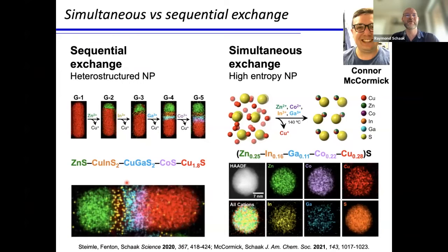And then finally, just to kind of show there's more than meets the eye to some of this, I showed these sequential partial cation exchange reactions that led to heterostructured nanoparticles. This is a 5th generation particle containing zinc sulfide, copper indium sulfide, copper gallium sulfide, cobalt sulfide, and copper sulfide. But if you do effectively that same type of exchange with the same cations simultaneously, where all metal cations are present, in this case with spheres, you end up getting a high entropy solid solution. So when you put everything together at once, you give it the opportunity to all mix, as opposed to temporally separating them through sequential exchange to get the heterostructuring.